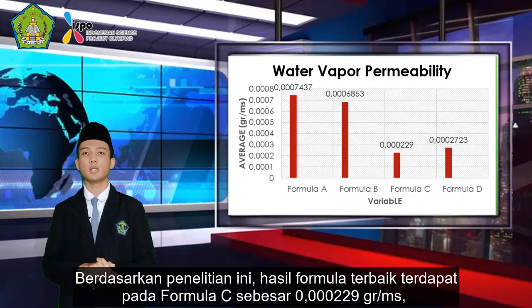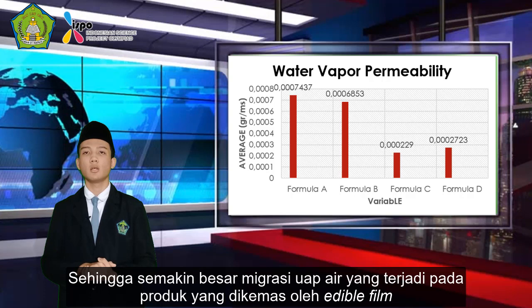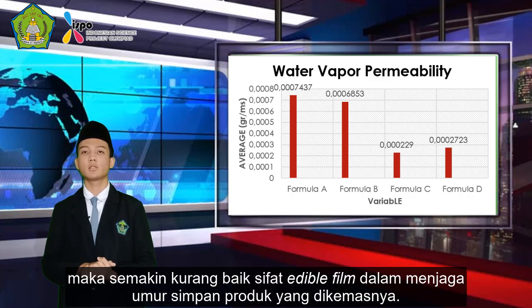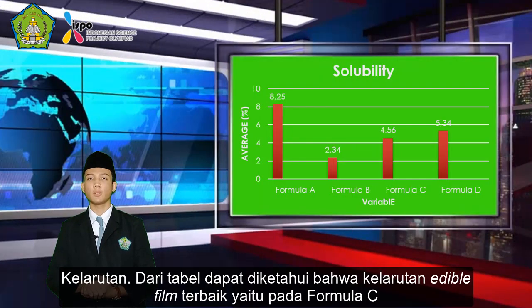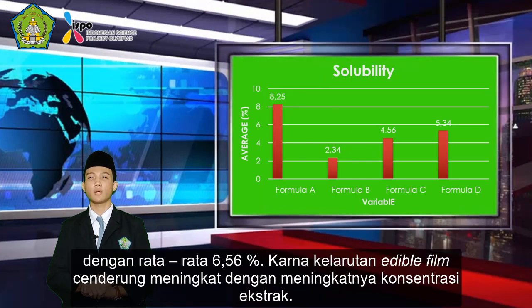Water vapor permeability. Based on this research, the best formula result is formula C at 0.000229 grams per meter second. So the greater the migration of water vapor that occurs in the product package by the edible film, the less good the edible film is in maintaining the shelf life of the package product. Solubility. From the table, it can be seen that the best edible film solubility is formula C with an average of 4.56%, because the solubility of edible film tends to increase with increasing extract concentration.